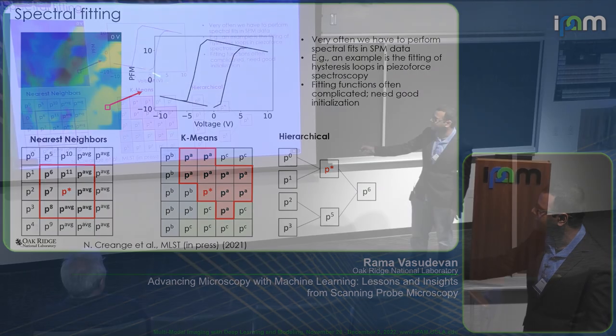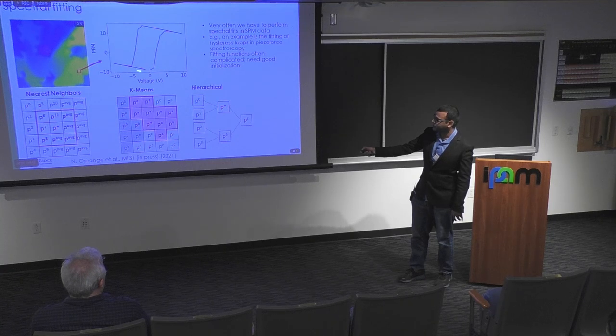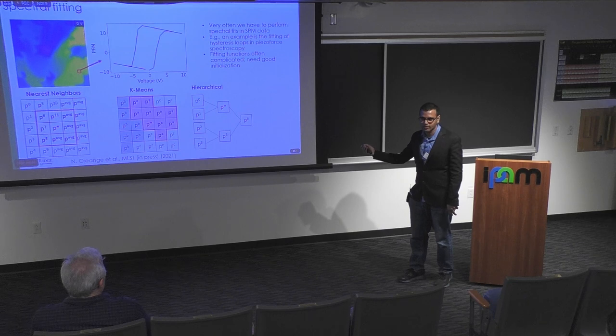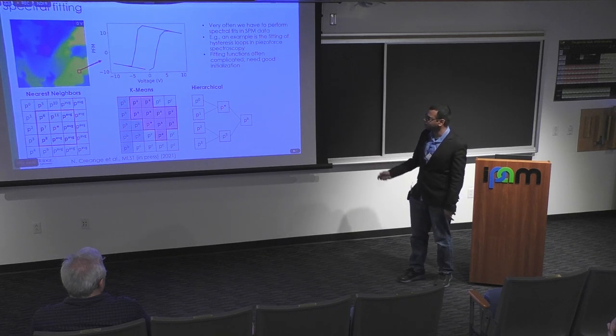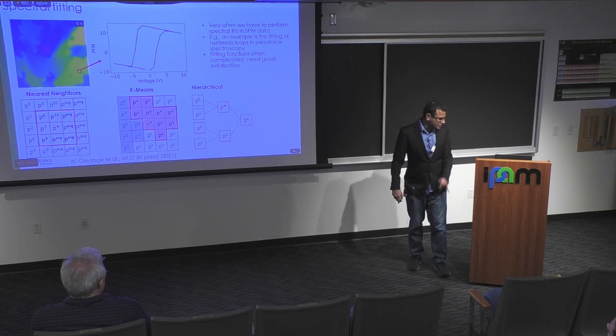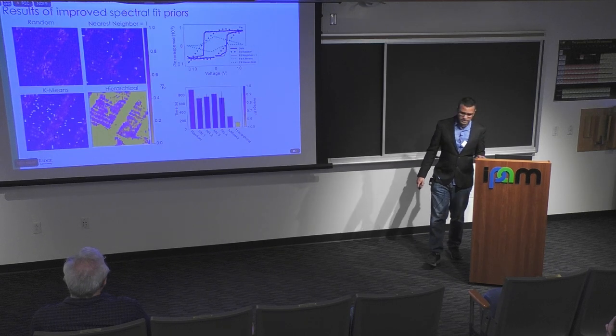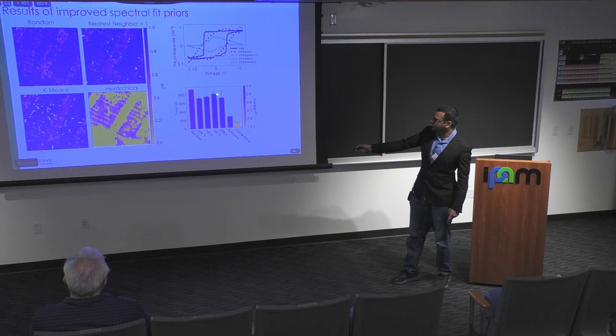Because for this particular kind of spectra that we capture, there are about 13 parameters in our phenomenological fitting function. And if you don't start with good priors for these kinds of functions, you're not going to get good fits. So, just to show that this actually works, this is the result.